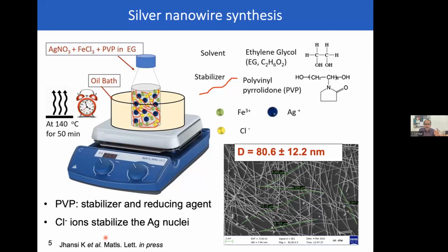Okay, so even if it's a nanowire, it is going to act as a bulk conductor, isn't it? Exactly. If you're asking about quantum effects, in metals, quantum effects only come when the dimension is of the order of a few nanometers. I have seen papers, and I know there's one group at IISc, where they have shown really thin silver nanowires, a few nanometers thick. There they can see some sort of quantum effects, but these all behave like bulk. There are no quantum confinement effects.